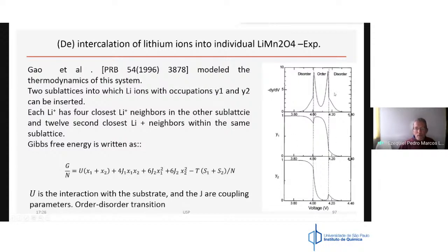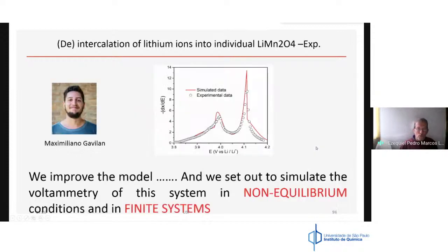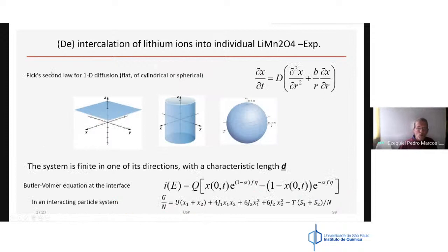Some people have modeled the thermodynamics, not the kinetics, but the thermodynamics, and we use the thermodynamic information to produce a more developed model. Again, Maximiliano made the calculations. So we fitted the voltammetric behavior at very, very low sweep rates, and from this information, we could develop a model to consider several sweep rates. So what we did is to solve for this system the Fick diffusion equations inside the material, coupled with the Butler-Volmer equation on the surface of the material. And we did this for different geometries.